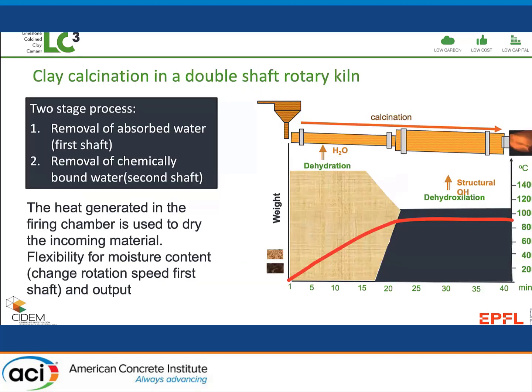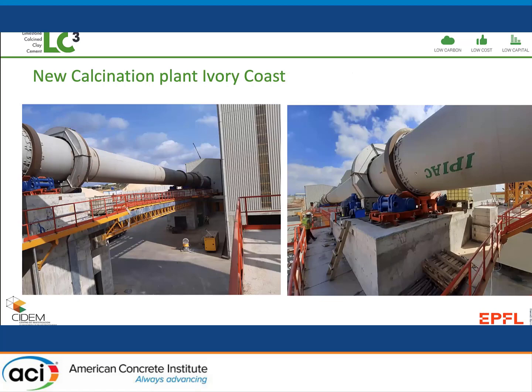Moving to more implanted industrial processes, one of the first permanent industrial processes in Ivory Coast, where they've installed this double shaft rotary kiln, which enables you to adjust the operating conditions according to the moisture content of your clay. And this is often important because according to the weather you have, whether it's rainy or dry, the moisture content of the clay can vary a lot. And it's quite convenient to have this kind of design because it enables you to operate on the best conditions with the minimum energy content according to the moisture content. So this is the fully installed kiln in Ivory Coast.